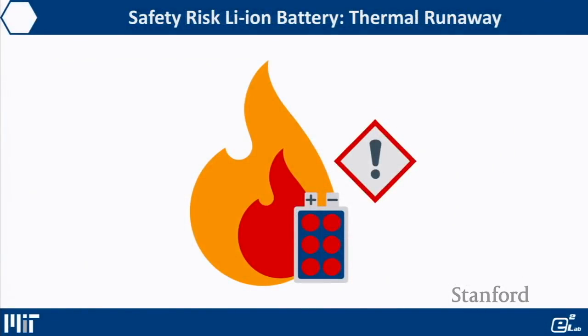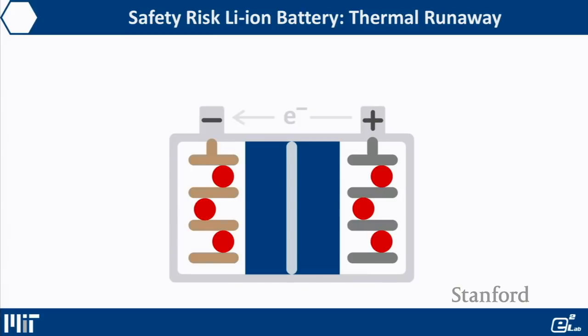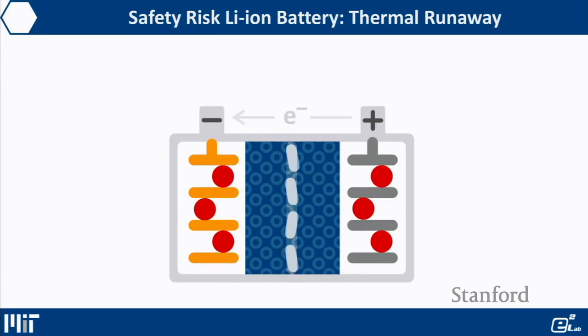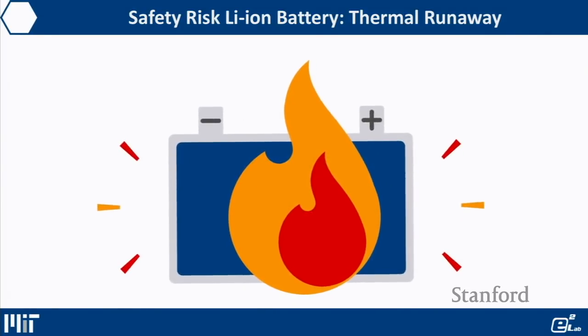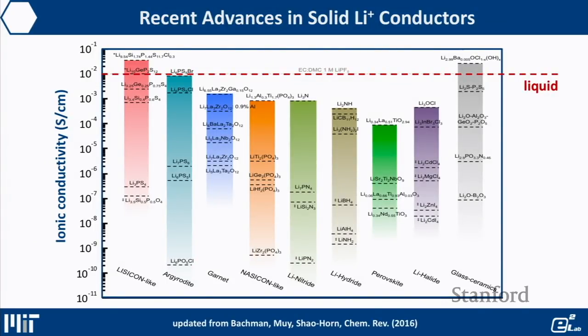But the technology we have today is not perfect. One would argue it is far from perfect. There is an issue of thermal instability, particularly upon charging of the batteries. The positive electrode can generate oxygen, which can react with the electrolyte. The electrolyte is organic, and this can generate heat and lead to thermal runaway. So there's a need to move away from organic electrolyte and replace it with safer solid-state electrolyte, either in polymer form or inorganic electrolytes.